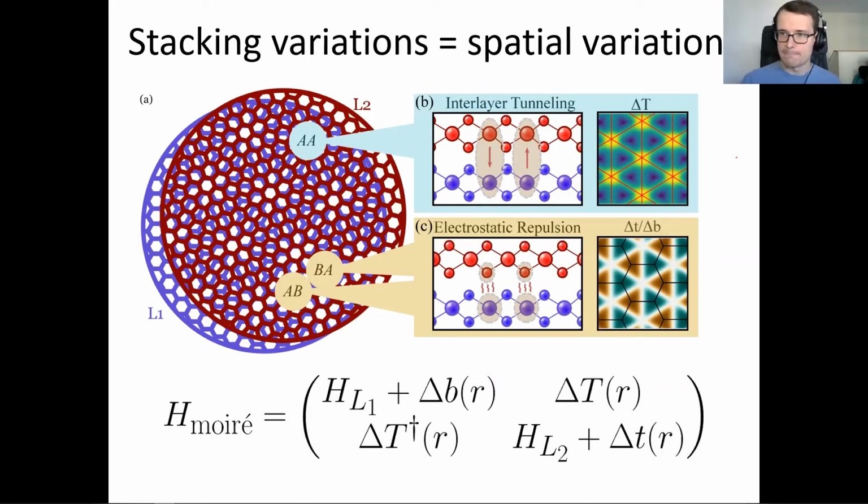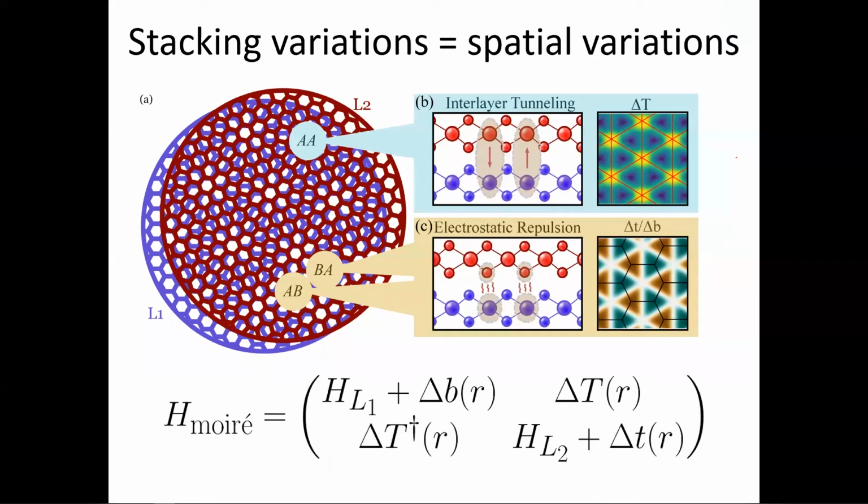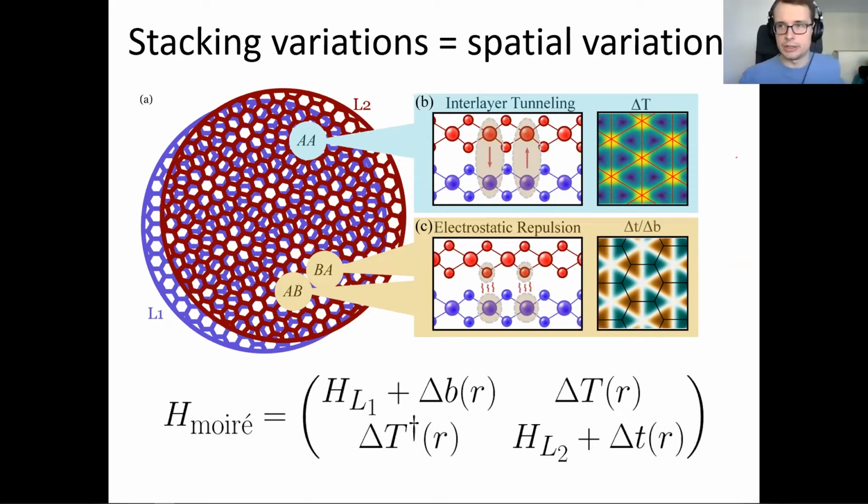Yeah. Thank you. Can I ask you a quick follow-up question then? Yeah, sure. So are you saying that your DFT calculations don't account for correlation in any specific way? That's a very good question, thank you. The DFT calculations are accounting for correlations on the scale of the unit cell. There's a DFT functional that deals with the correlations due to the electrons as they move around the atoms. However, with these sort of calculations and these multi-scale techniques, until you add it by hand, there's nothing that takes care of correlations that are happening at the scale of the Moiré unit cell. So on this larger length scale. Yeah. Thanks.